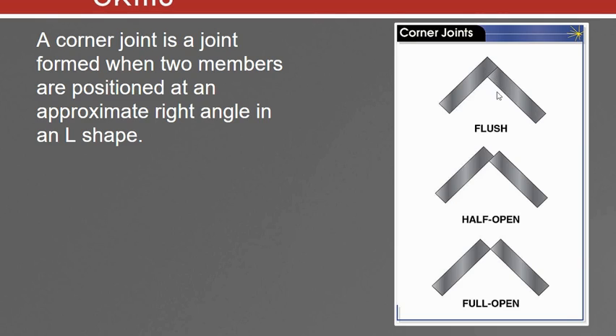I don't recommend this per se because you're getting a weld here and then a weld here with no joint preparation. You have a lot of weld that is not penetrating in any. If anything, I would overlap it slightly like this, a half open or even a full open joint. This will ensure that you get 100% penetration. This is going to give you 90 or so percent penetration without joint preparation.